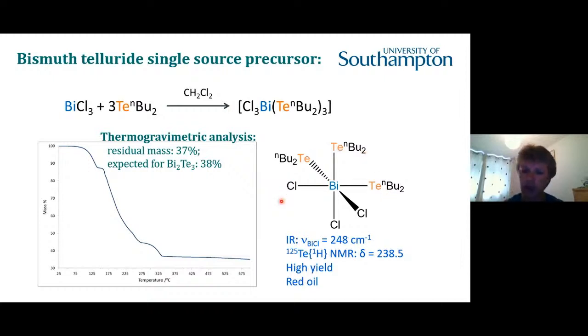And Chitra worked on this molecule. This is bismuth trichloride with these butyl telluride ligands coordinated. This is a red oil. It's formed in very high yield from the scheme shown above. And the red oil tells us it's got some vapor pressure.